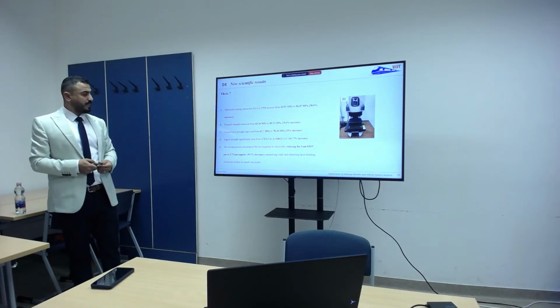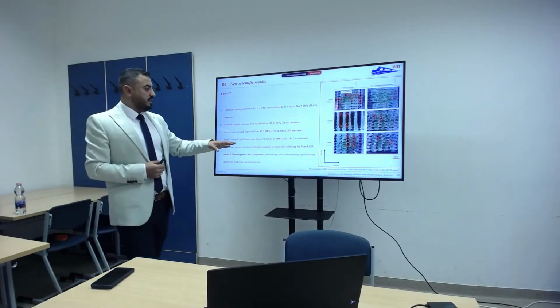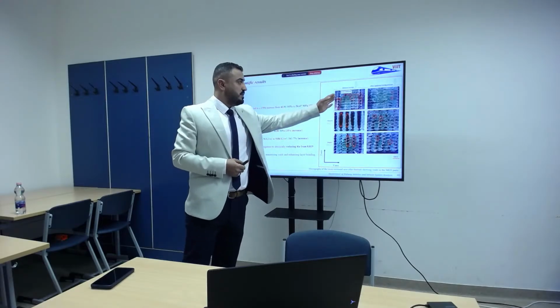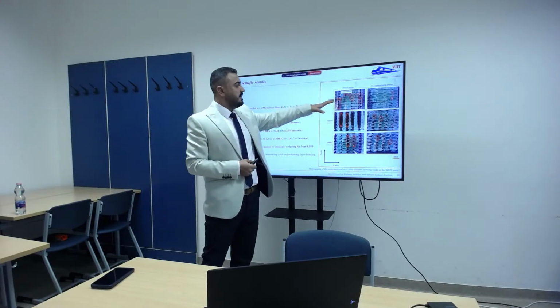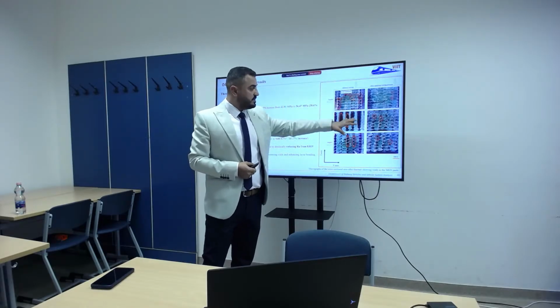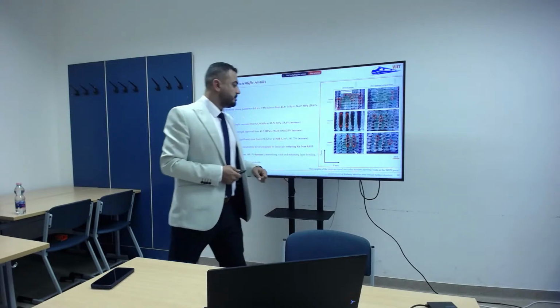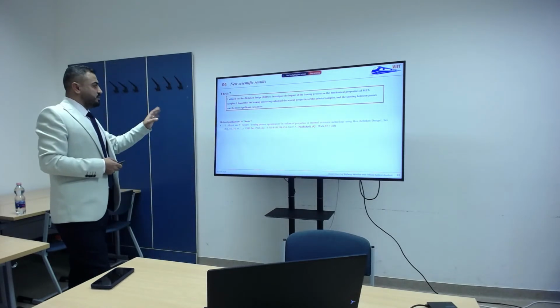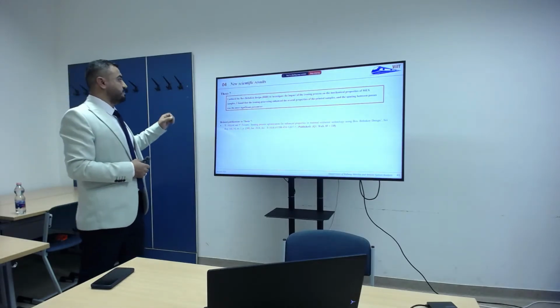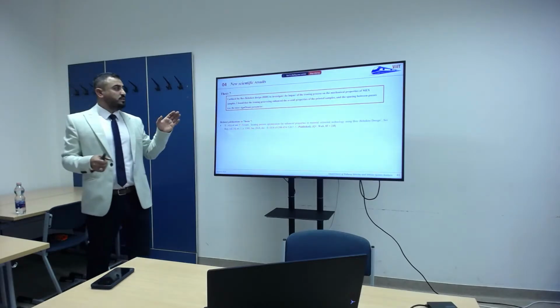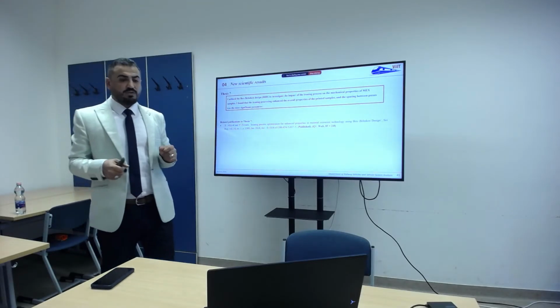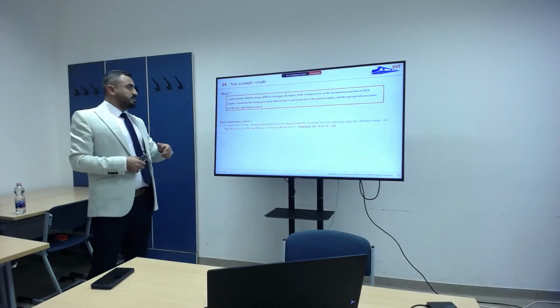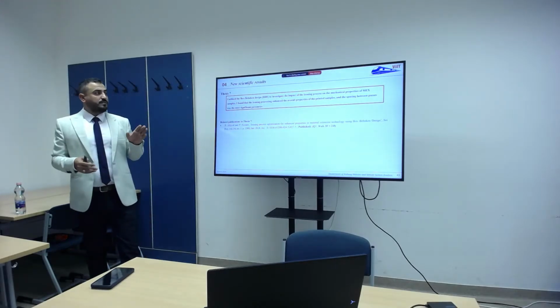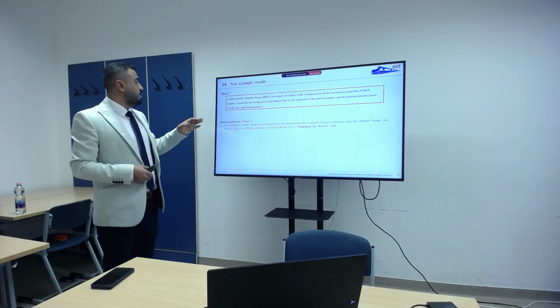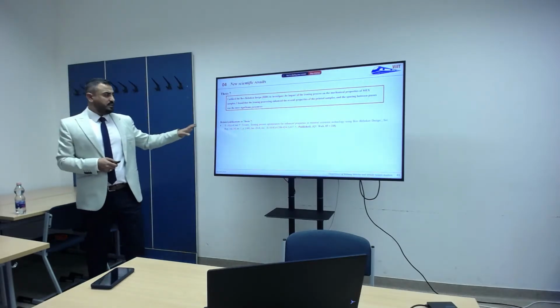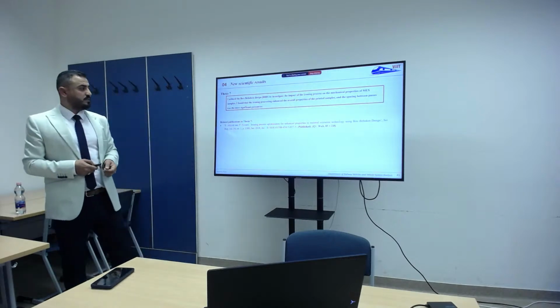And here we can see the micrographs of the cross-sectional fracture area without ironing and after applying ironing. Here we can see how the voids affect the tensile strength and how they were eliminated after applying the ironing post-processing. So thesis number 7 stated that I applied the Box-Behnken design to investigate the impact of the printing process on mechanical properties of material extrusion samples. I found that ironing enhanced the overall properties of the printed samples, and the ironing spacing was the most significant parameter. And here is the publication where I published my results in a Q1 impact factor journal.